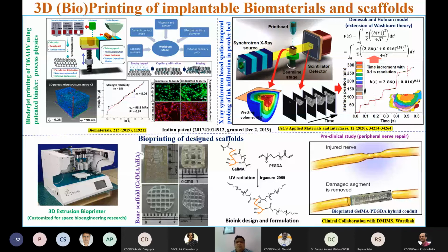So we have taken several materials, but this particular slide, the left-hand side, shows titanium, because this is one of the FDA-approved materials, and it shows the strength reliability as far as the Weibull plot is concerned around 8. So the strength reliability in terms of the M parameter is 8 in this kind of highly porous microstructure with 98.4% interconnected porosity, which is quite an impressive number. Now, in terms of the cytocompatibility, it shows very good cell proliferation, and it's certainly better than commercial Ti6Al4V, and that is expected because of the porosity in the structure.